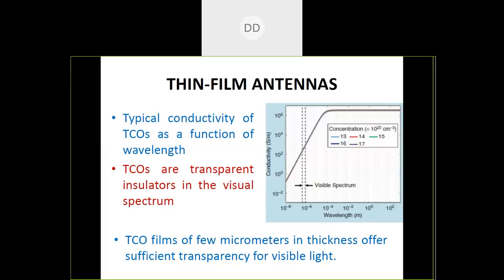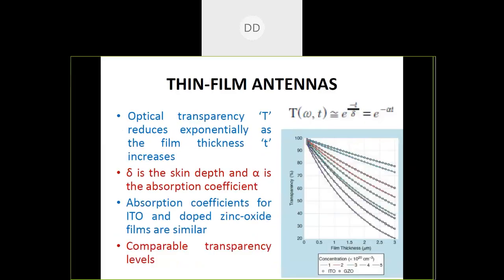of antenna. Another parameter is that the optical transparency T reduces exponentially as the film thickness increases. So as we increase the film thickness, the transparency will decrease. That means the thickness should be very small. This relation is given between the transparency and film thickness. We can see that the film thickness is related to the skin depth as well as the absorption coefficient. So delta and alpha are involved in the calculation of transparency of the antenna.